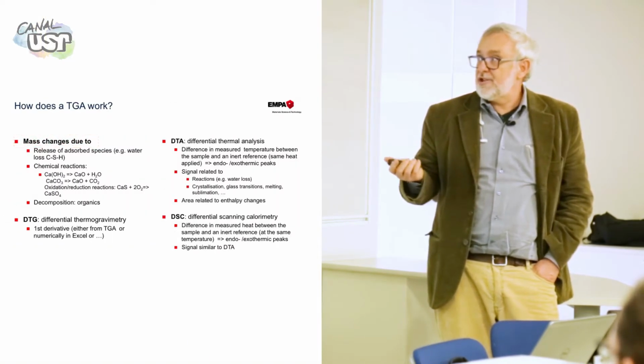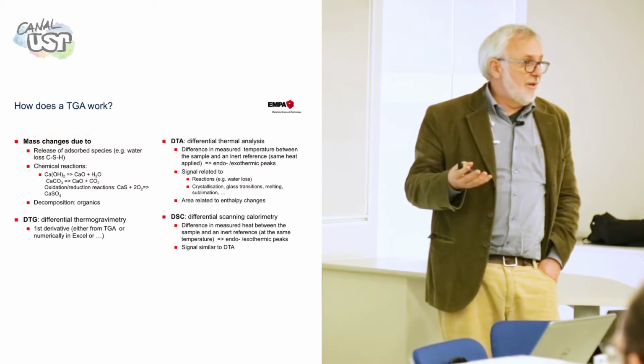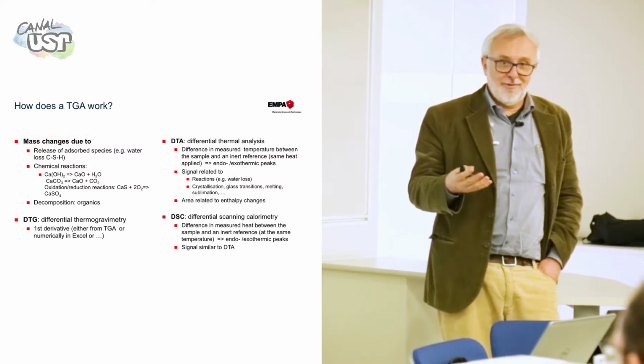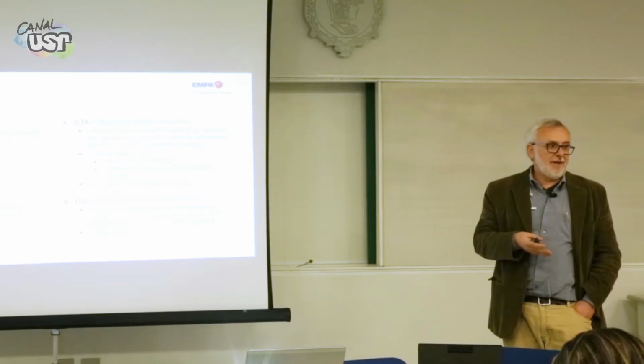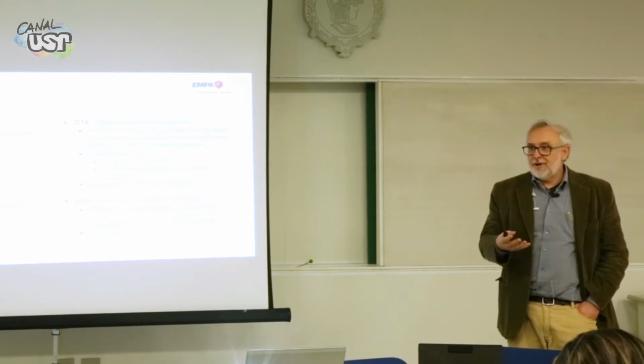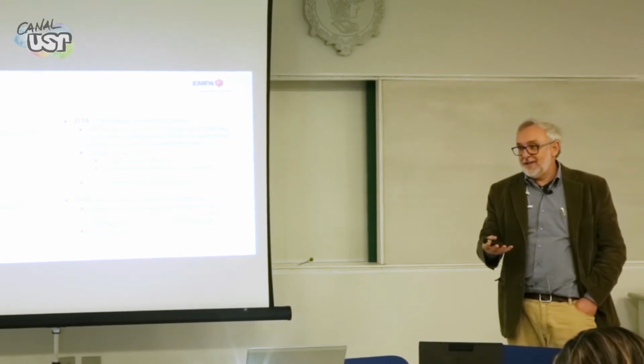How does it work? Well, what we record is mass change, and mass change is water loss. So drying properly without destroying the sample is very, very important. You have to dry it, but you cannot dry it too much. You decompose ettringite, and there is a lot of water in ettringite. You lose a lot of water from calcium silicate hydrate because the water is not chemically bound, it's absorbed. So you have to be very careful on drying.